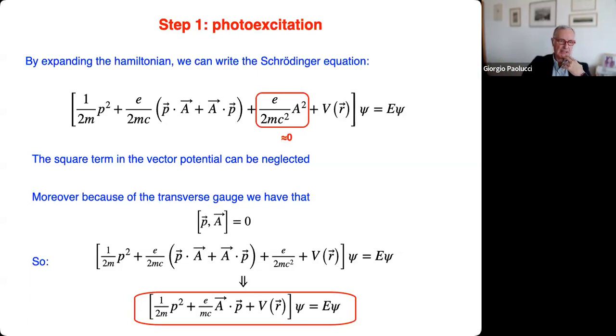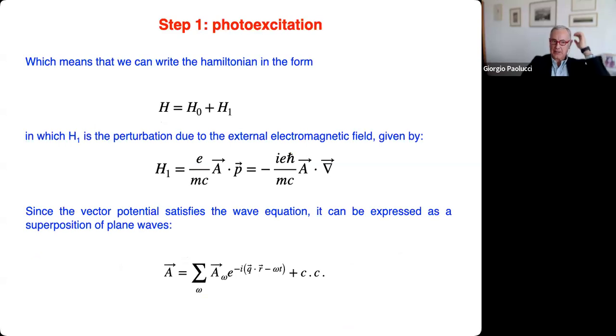And so you do some basic algebra, and you come up with this formula in which we have neglected the square terms. The square term e over 2mc squared times A squared, because we know that A must be small with respect to the atomic electromagnetic field, so that term can be neglected, and it is moreover divided by c squared, and we know that c is a big number, so we neglect that. That is a good approximation. And so we come up with this equation, which is exactly what we want, because this equation is in the form of the basic equation of the electron in the sample, plus a perturbation, which is this A dot P term.